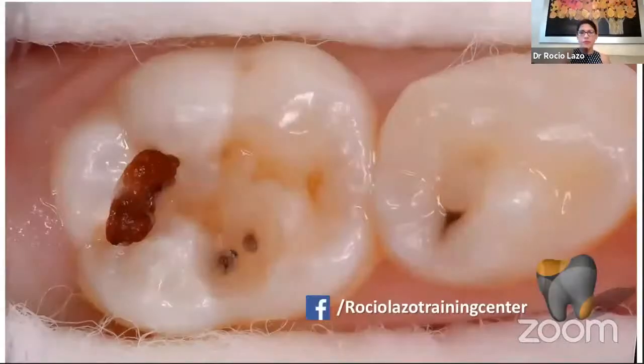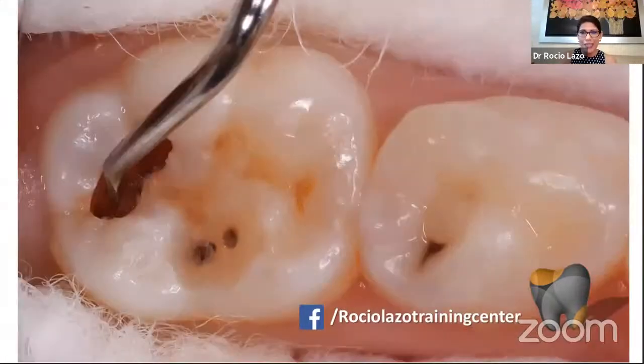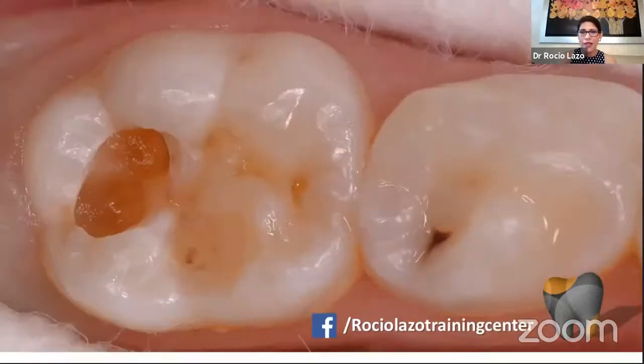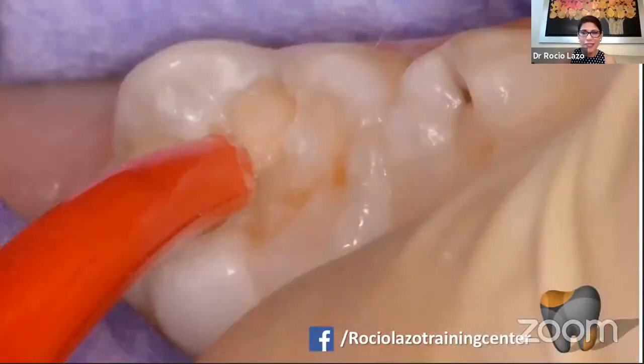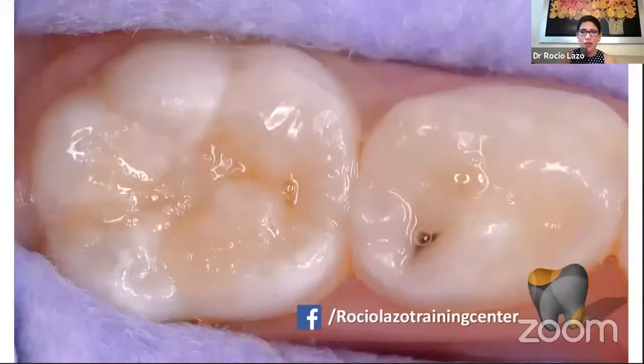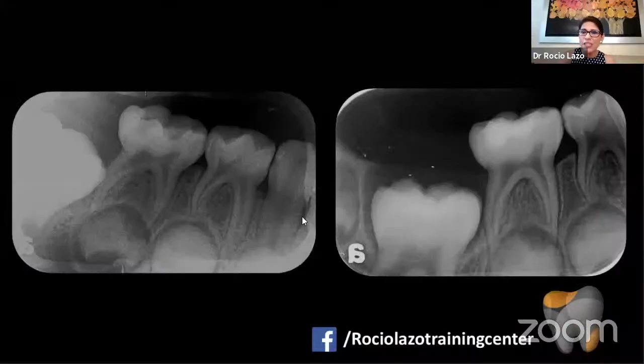This is the Riva Light Cure, high viscosity, that has strontium, and it works perfectly. And look here, this is Riva Light Cure, a glass ionomer modified with resin, with fluoride and strontium, okay? If we want to do a minimally invasive treatment, for example here, we are going to remove the infected dentin, and we are going to work in the affected dentin, okay? Then we apply the Riva Light Cure, high viscosity, and look here, it's perfect aesthetically, and the X-ray is perfect.